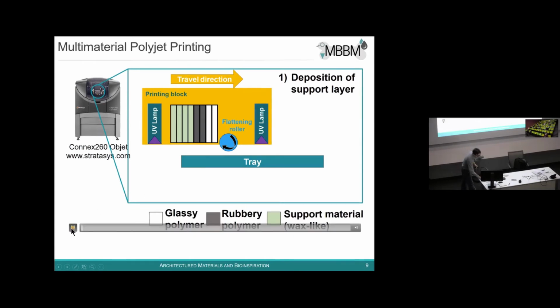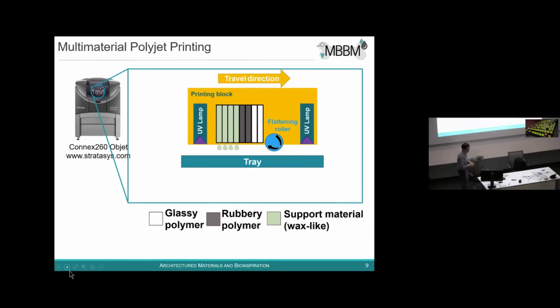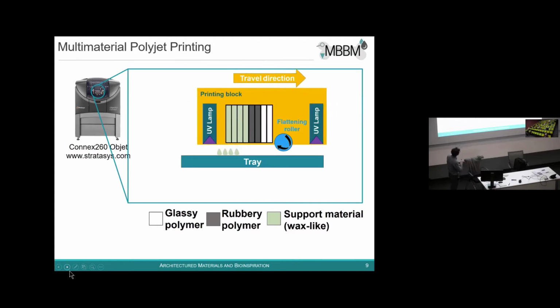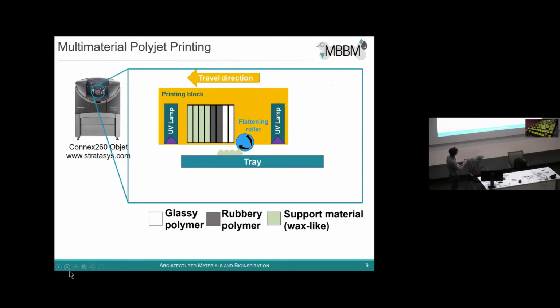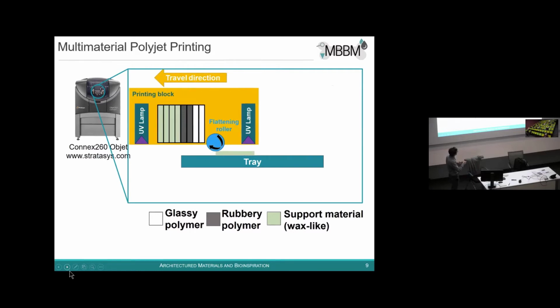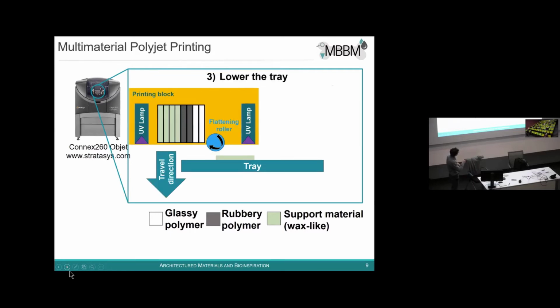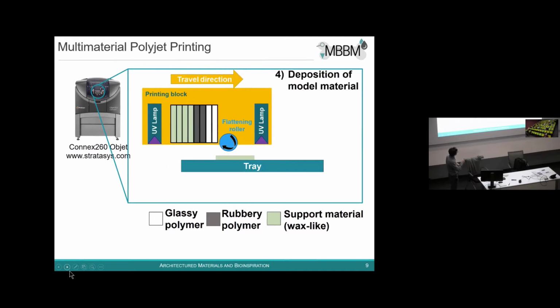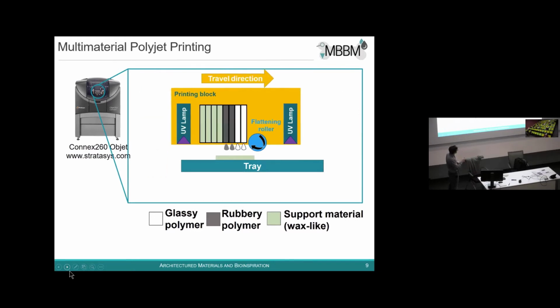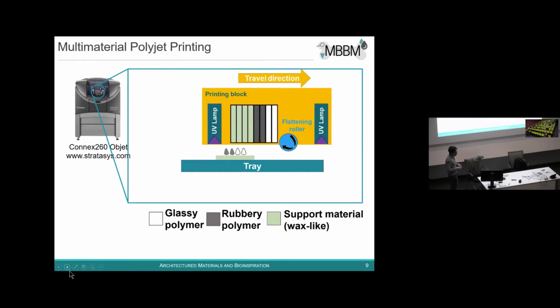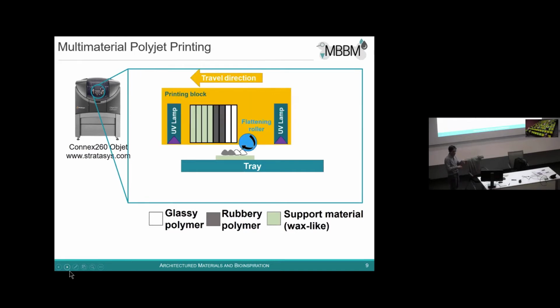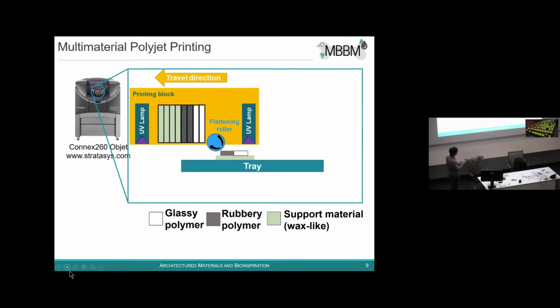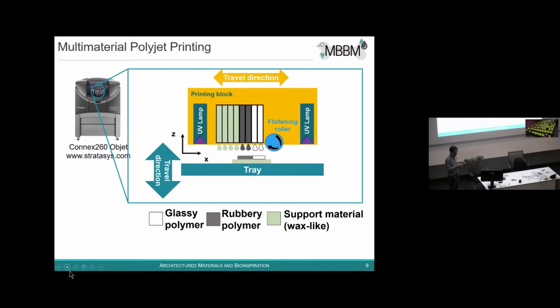I think there is even a small animation. Yes, so the printer head is moving from left to right, depositing droplets of different polymers. They are deposited on the build tray, flattened down by a roller and then cured by UV light. And typical droplet dimensions are about 20 micrometers, and this is of course a layer by layer technique, and layer thickness is about 20 micrometers. So that's the theoretical resolution of the printer.